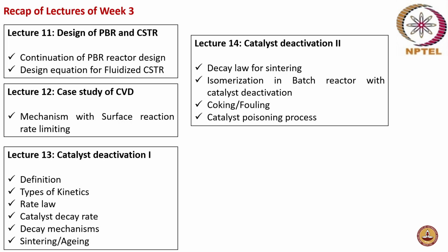In most of the cases, these noble metals like platinum are placed in some materials, like you would have seen when you are writing catalyst reactions, Pt/Al2O3. Okay. So in this case this platinum catalyst is impregnated on the alumina surface. This alumina will have a lot of pores in which this platinum will get placed. Due to prolonged exposure, this platinum starts getting agglomerated, and this agglomerate starts growing. Instead of being in multiple places, they all combine and form a big agglomerate.